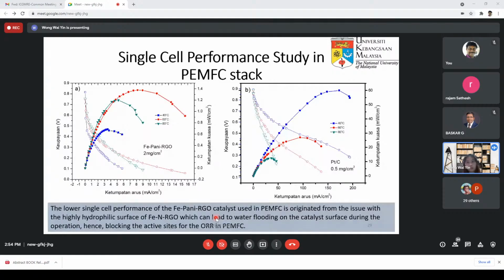So this is one issue in the Fe-N-C catalyst that has to be further studied, probably in terms of how we can improve the water management in this layer. For example, how to incorporate a hydrophobic agent on the surface, as well as how we can tune the pore size of this catalyst layer in order to facilitate the transfer of the water itself.